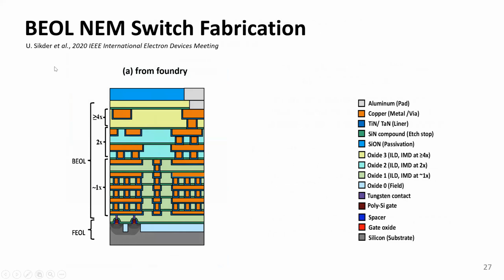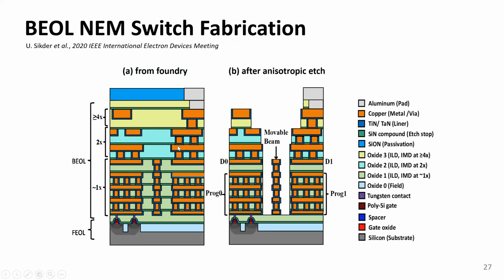First, let me tell you how we fabricated these at UC Berkeley. This schematic cross-section illustrates the back end of line layers in a typical CMOS foundry process, which has been patterned to form the single pole double throw switch shown previously. The upper metal layers are patterned to form a hard mask for an etch process that is performed at UC Berkeley after we receive this chip back from the foundry. This etch process removes all the many layers of dielectric material, and this can be more than a micrometer thick, and the air gap here is approximately 100 nanometers. So we use reactive ion etching with an inductively coupled plasma, and in between we use some wet etching to remove polymeric byproducts during the reactive ion etch process.